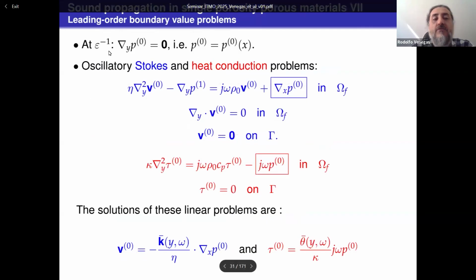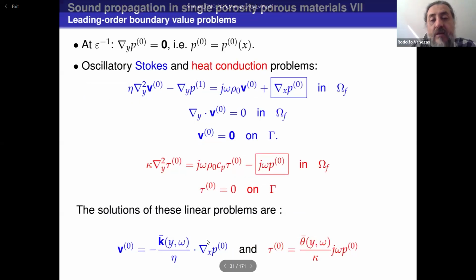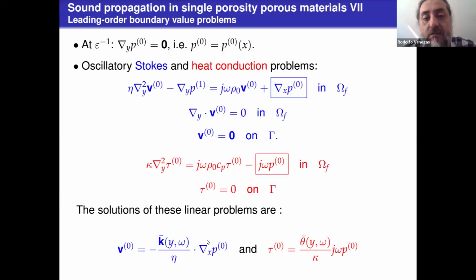and we then identify the terms of different powers of epsilon. So at epsilon minus 1, we get that the gradient with respect to the local variable of the leading order pressure is equal to 0, which means that the leading order pressure doesn't depend on y, but rather just on x, which is the macroscopic variable. Here I have to say that we have used a little bit of notation because we got rid of all these stars, indicating that this is adimensional, but this is just a conventional way of doing it so that the notation doesn't get too clumsy.